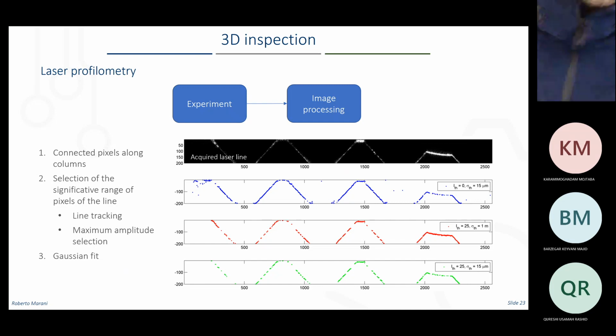So in laser profilometry, if you remember, 2 days ago I showed you that experiment with the drilling tools. This is the profile acquired using a camera from the side of a drilling tool. There was a defect here. This is something that is missing from this tip. I don't have a tool here, but on the side of your tool, we are just looking at the teeth. And then you can reconstruct this line. So okay, you're able to see.